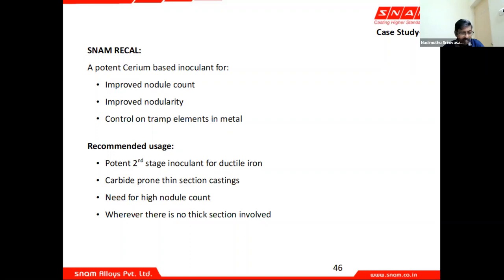That is why the addition rates are lesser in the second stage, because there is no discrimination between returns of a thin section casting and a thick section casting. The returns are the same. So for carbide prone thin sections, you can use it. Where you need a high nodule count, you can use this.